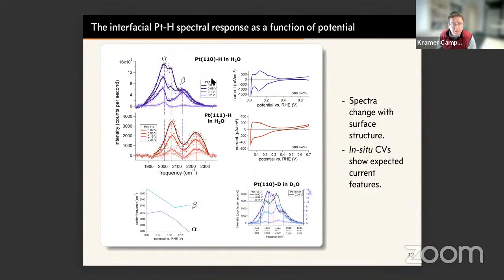The situation looks quite different on platinum 110. Here, one sees perhaps the same spectral feature and two additional ones as well that I've labeled alpha and beta. There is some spectral interference going on here. We can discuss in depth where that might come from if you're interested. This is a consequence of this being a coherent optical spectroscopy. And you can see quite clearly that the voltammograms are not nearly as pretty as the ones in the meniscus geometry that we collected before. This is perhaps to be expected for minimal contamination from the window, but mostly because to do this measurement, we make this gap very small, and it is very challenging to do reasonable voltammetry under situations where you have this very thin film of electrolyte above the working electrode.